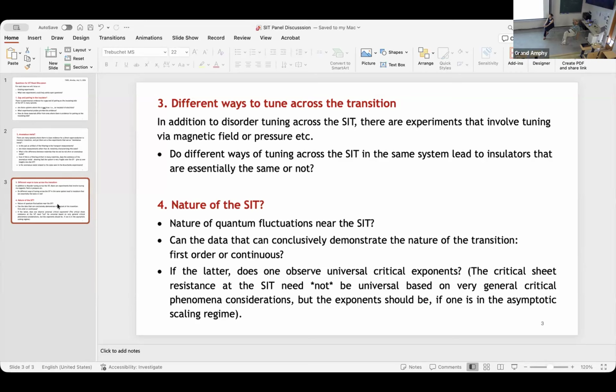This is just observation. The idea would be that basically every material shows this, but sometimes not. We are talking about an insulator after you kill superconductivity. You need to have an insulator to have this. Yeah, of course. If you take molybdenum germanium, you end up with a bad metal. Yeah, you see a disordered metal. So this is not the same story.